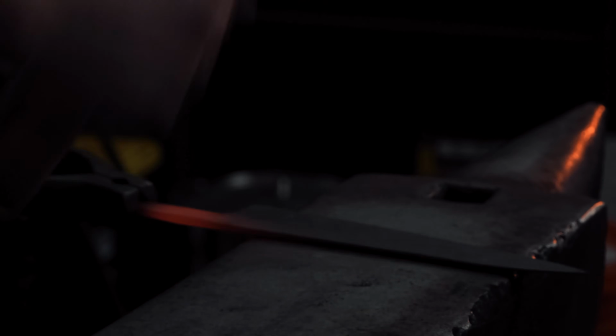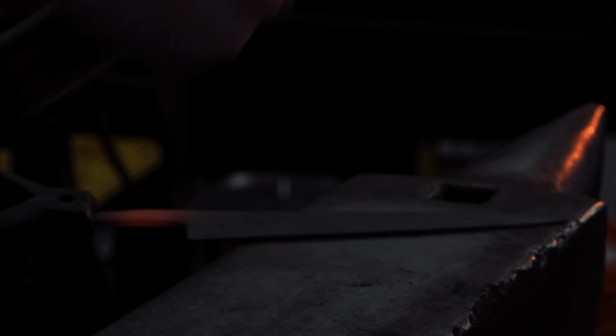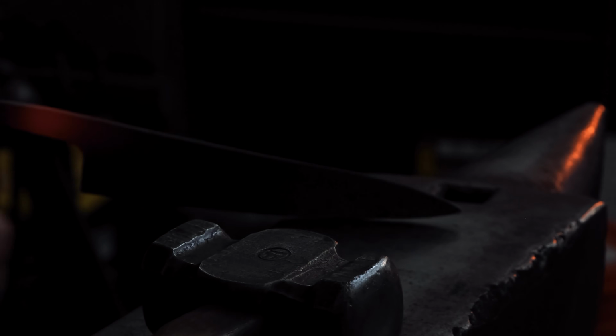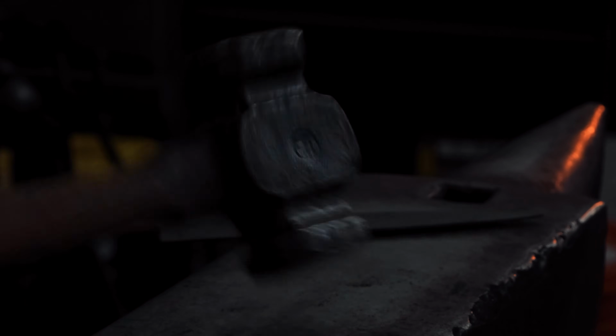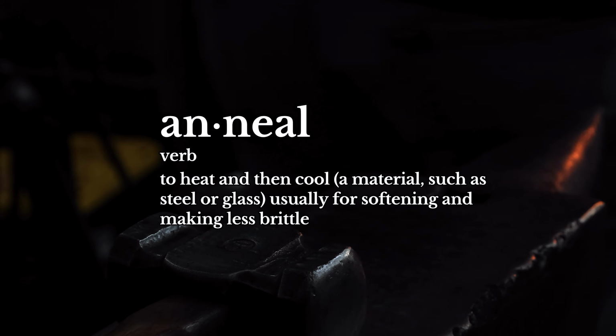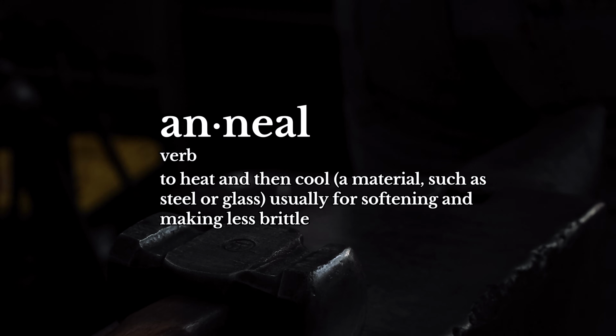And I reduce the heat, and I basically get it so that the last few heats I'm forging at as low a heat as I can get away with to refine the surface texture, the grain, and from there I'll go to my kiln, my very precise, expensive kiln, and I will do some more thermal cycling, normalizing, grain refinement, and annealing. After I anneal, I do some cold work on these knives.